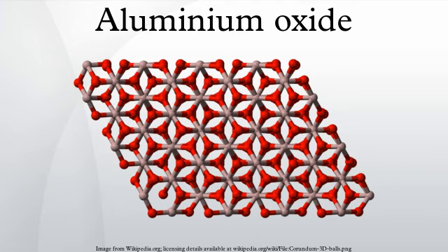Molten aluminium oxide near the melting temperature is roughly 2/3 tetrahedral, 1/3 5-coordinated, and very little octahedral AlO is present. Around 80% of the oxygen atoms are shared among 3 or more AlOx polyhedra, and the majority of interpolyhedral connections are corner sharing, with the remaining 10–20% being edge sharing. The breakdown of octahedra upon melting is accompanied by a relatively large volume increase. The density of the liquid close to its melting point is 2.93 grams per centimeter cubed.